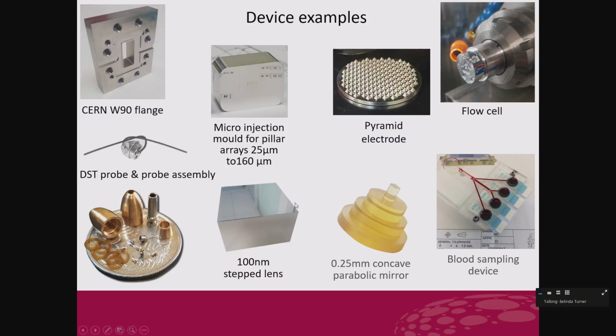So we made this as a test part for after we moved the Kira to a different location. And we had 100 nanometer steps. So the edge of this part, which is about this size, is actually 3.4 microns lower than the middle. But you can see if you come and have a look at our facility, you can see where I get to the corners and I slow down the cutting parameters, and the pressure's there for a bit longer. It actually goes deeper. So there's lots of other things to consider.